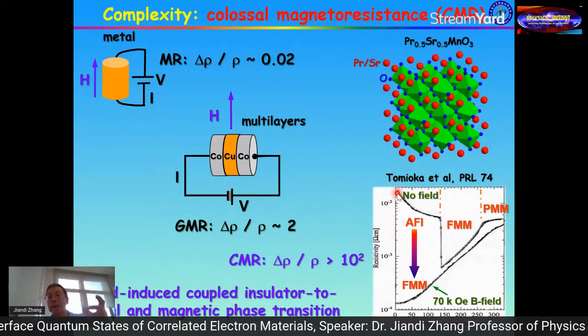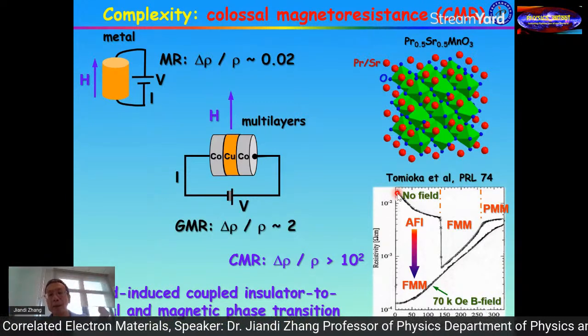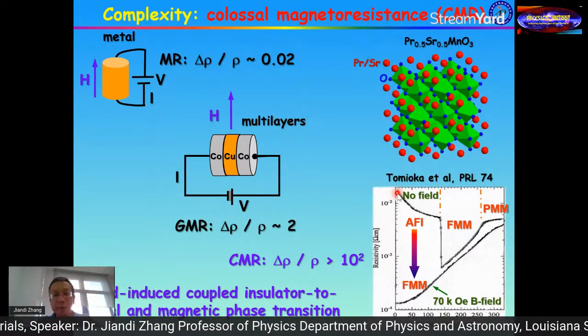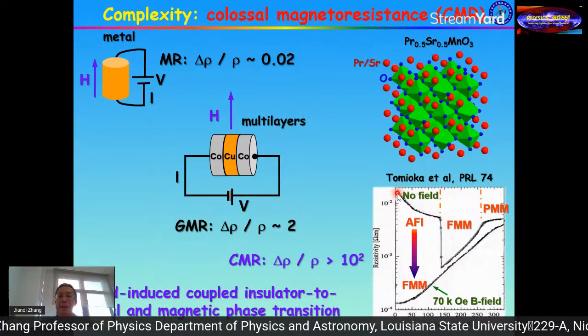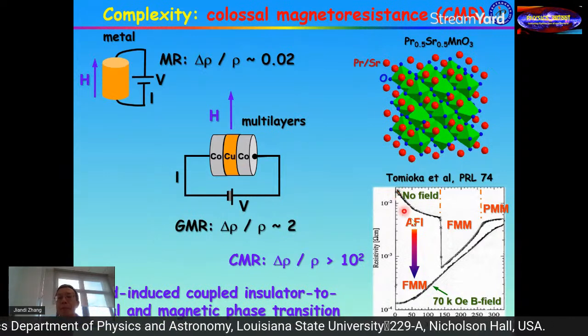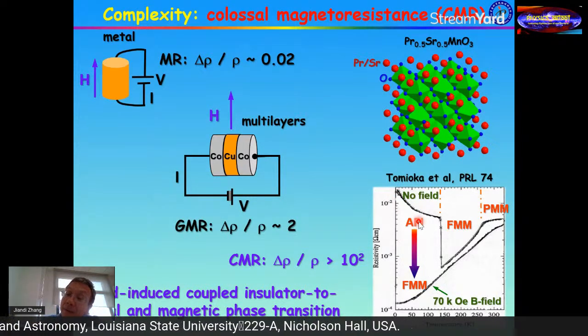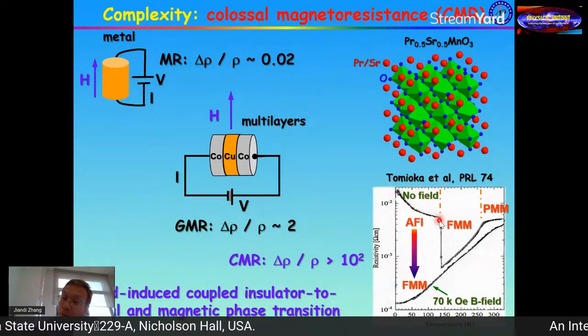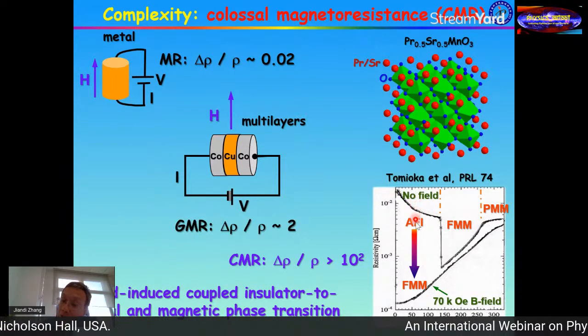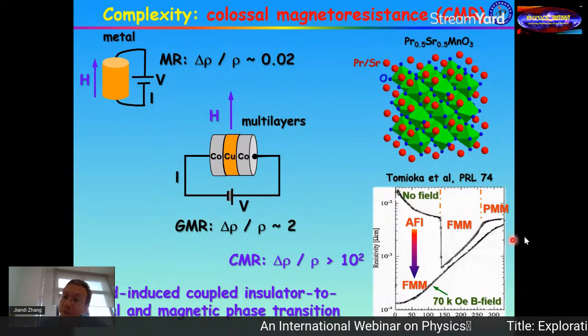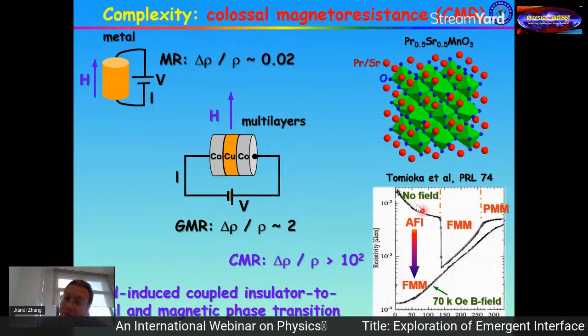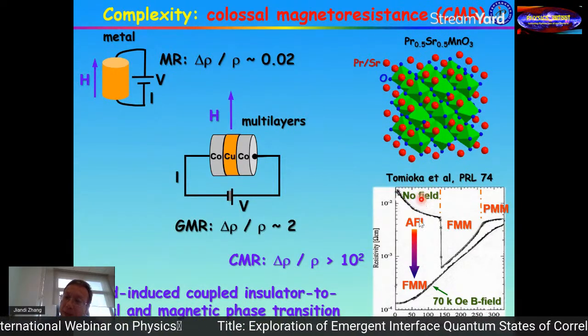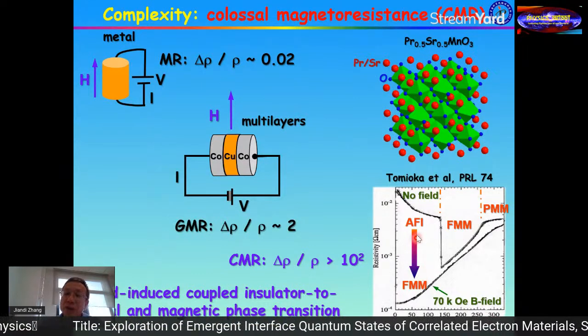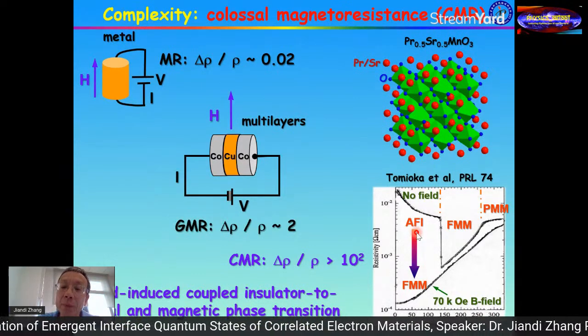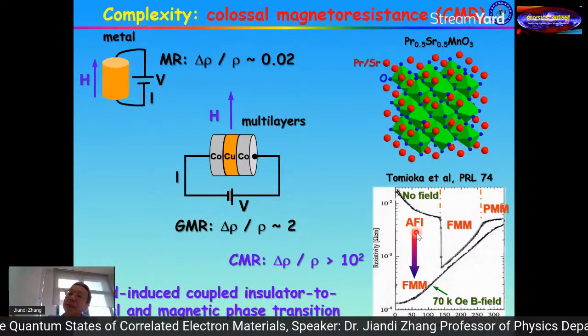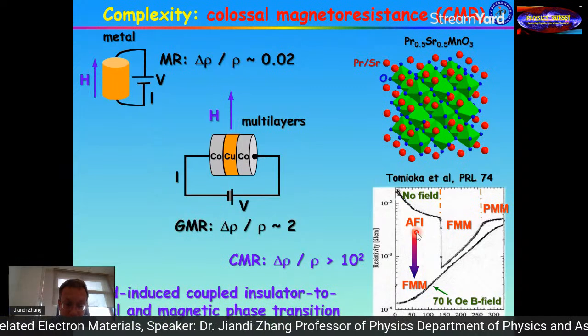This is just one piece of compound, but it's different from a metal, different from a semiconductor, because it has such a complicated behavior for different phases. And now, even more interesting, suppose in this low temperature range I apply a large enough magnetic field, and I find, my God, the phase can change from the insulating one to a metallic one. And this is not just giant magnetoresistance behavior. It can actually turn the insulating state into a metallic state.